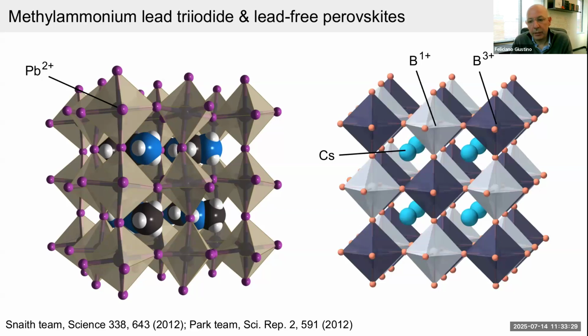Now we moved on to something a little bit more complex, but still doable, which was to consider that instead of replacing just one lead element, you may try to replace 2 lead atoms. Instead of having a 2+, you could have a 1+ and a 3+. For example, you could have silver on this side, and bismuth on this side, and the total charge neutrality is maintained. And the other thing we did is to replace the organic molecules, which are actually responsible for a lot of the instability in the system, by simple elemental cations.